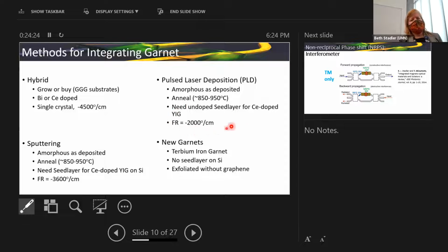The interactions they report between the substrate and the film are pretty low, except they do have a few recent reports where they've used our terbium iron garnet and gotten actually some pretty good Faraday rotation out of doped terbium iron garnet. Terbium iron garnet is one that my group kind of figured out by looking at the cation ratios—how can we make sure we get the garnet to form without forming those other phases? And terbium iron garnet doesn't need to be seeded on silicon to still give you a good crystal structure.